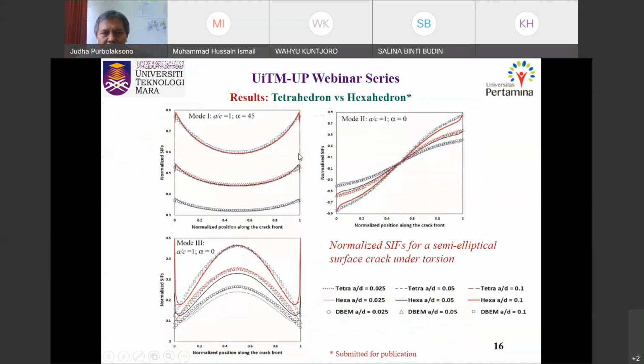Okay, here is the trend. We can see the results between the tetrahedron and hexahedron are quite identical. The only problem is that with the hexahedron, we cannot get a good result at the corner point. Also in mode 3, the solid line here is from using the hexahedron, and the comparison with the dual boundary element result is a bit shifted away. If we use tetrahedron, it's in good agreement, but of course at the corner point we still have a problem in mode 3. For mode 1 and mode 2, they are in good agreement.